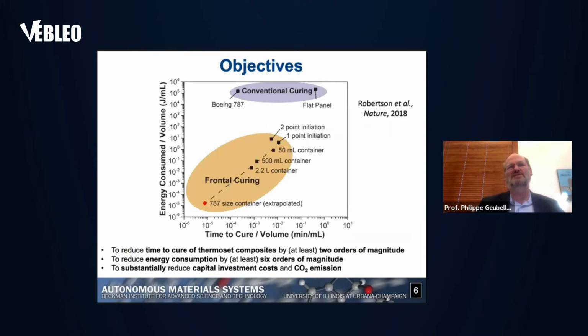bit about how these materials are actually made. We display this in a schematic form, showing on the y-axis the energy consumed per volume, and on the x-axis the time to cure per volume. The 787 will be up here. It takes multiple hours in an autoclave to make these very, very large parts. What we want to do is to reduce it and bring it over here. That's the objective. The dark symbols over here are parts that we've already made.